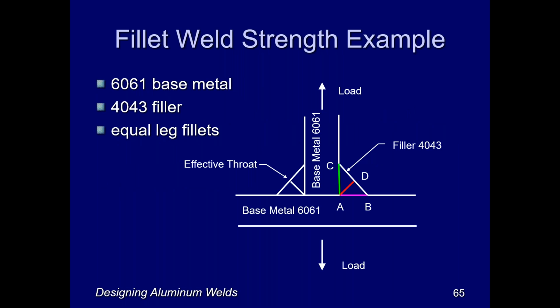So here is an example of a T-joint, and we have 6061 as our base metal and 4043 as our filler metal. And in order to design this weld, if they have 4043 filler metal, you would look at three lines of stress. The line that's represented by AC, or the green line, and that would be shear in the base metal. The line represented by the purple line, the AB line, which would be tension in the base metal. And then the red line, the throat of the weld, or the AD line, representing the shear on the throat of the weld.